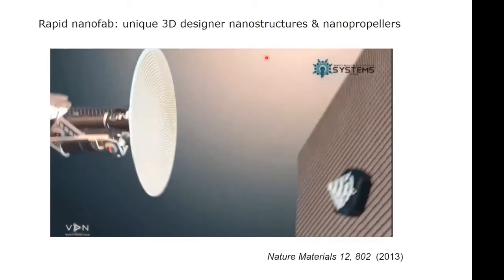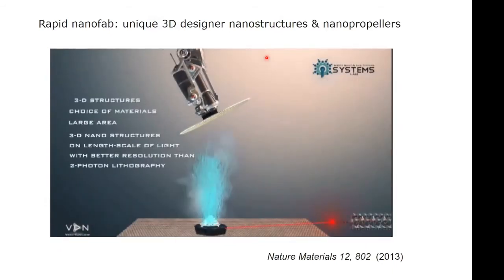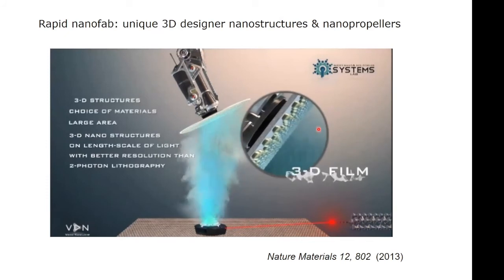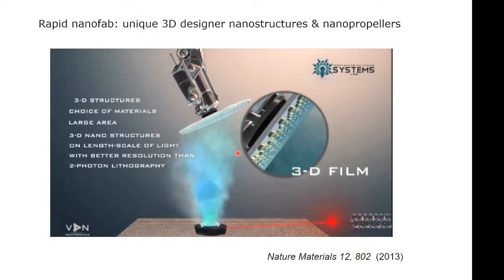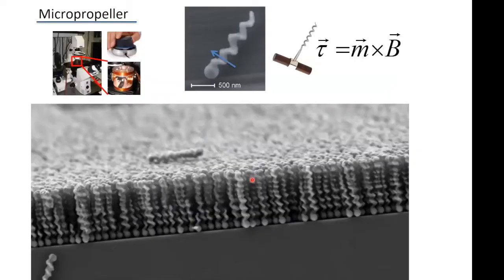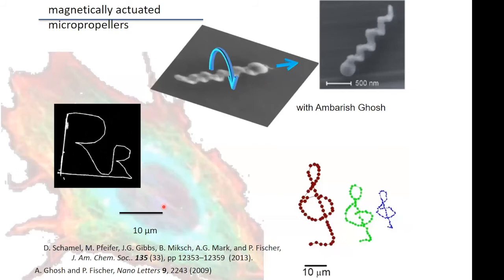And so in this particular case, this is an animation. We will heat the material, we will have the angled substrate, and we can start angling and rotating it, changing materials and getting shapes. One shape that is interesting and very effective is this drill shape, which is the same length scale as a bacterium. It's now made out of artificial materials, if you like. It can be silica, it can be oxides, metals, whatever we like. And we can include a small bit of magnetic material, so we can exert a torque on it. Then it's a bit like a corkscrew. And these we can control very, very well in solution.